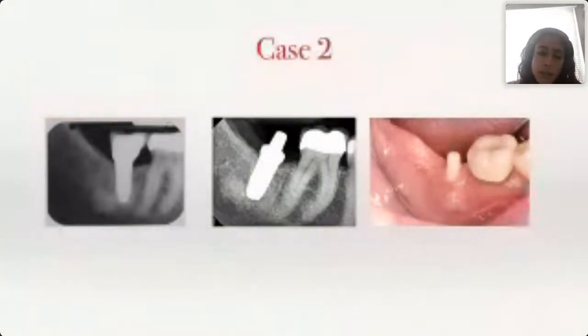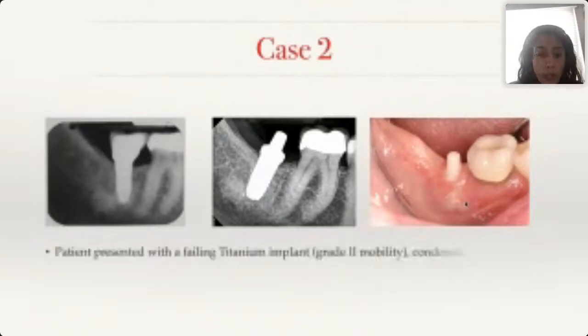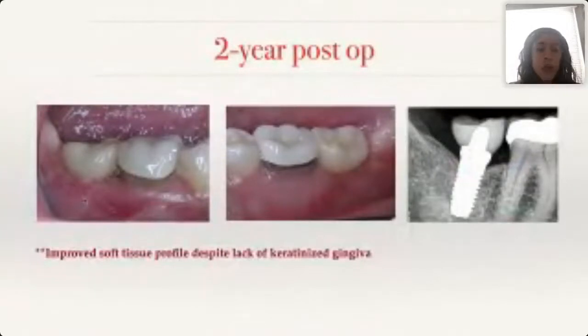Case 2: this implant had mobility, the titanium implant was failing, and there was condensing osteitis. It was removed, and I replaced it with a zirconia implant. In this case, we can see there is almost no attached or keratinized tissue - it's in the posterior mandible area. This is following restoration, so no recession, 2-year post-op, even in presence of no keratinized tissue, we get very nice attached, healthy gingiva around these implants. So this is very special about zirconia implants.